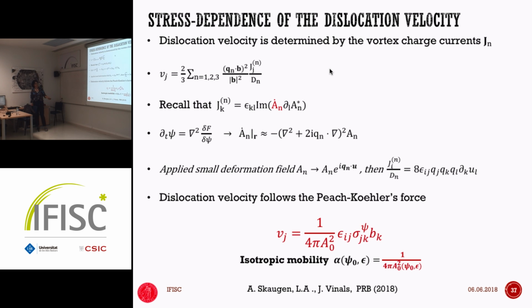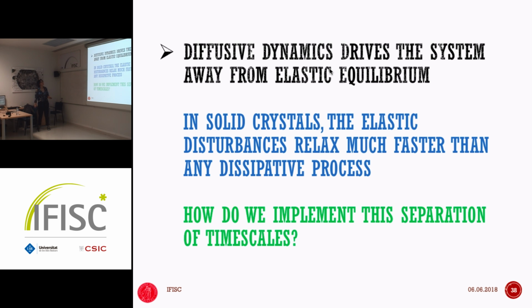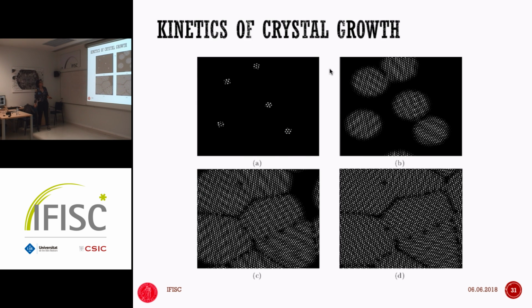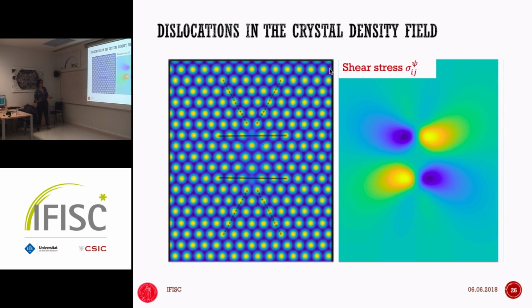And the interesting thing is that the mobility that we can predict within this approximation is the same, both if the velocity has this climb motion or this glide motion. So I didn't talk about this, but basically when we have these dislocations in a hexagonal structure, they can go, here. You have this dislocation here. It can either glide along the Bragg plane, it has one velocity, but you see it can also move this way, in this direction, and that's climb. And this direction typically requires an energy barrier. So at high temperature, it can climb, but at low temperature, it's mostly glide motion.